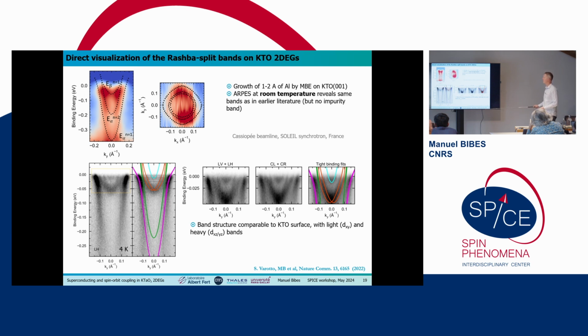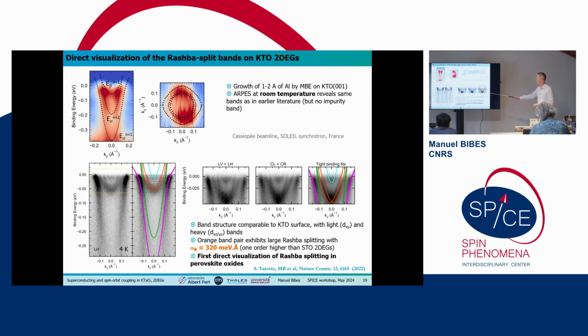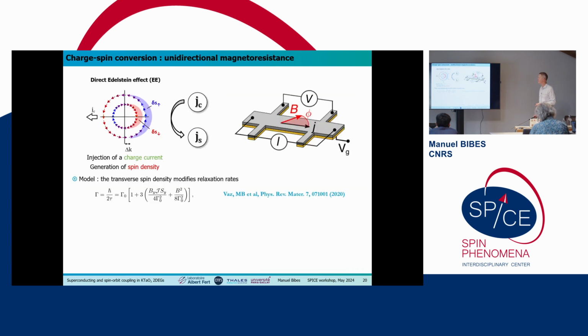Okay, so there's a quite complex band structure with 2 pairs of bands. One pair has maybe a Rashba splitting, but very, very small, resolved by the ARPES, and another pair of bands has a much larger splitting. We estimate the Rashba coefficient to be about 300 meV angstrom, which is in this case much larger than in the case of STO, as we expect from the presence of the tantalum. And these experiments are very challenging. This is the first time Rashba splitting has been visualized in this type of oxide.